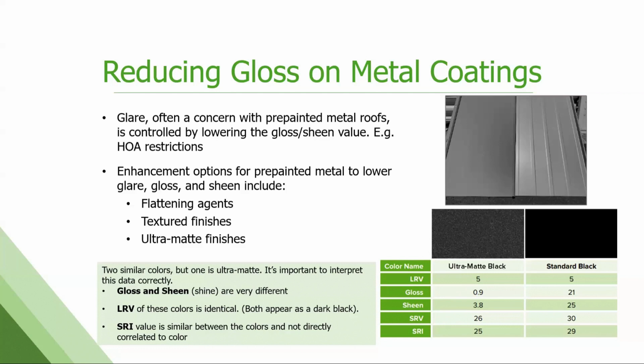We can kill the gloss or the sheen on a product a couple different ways. We can use flattening agents. We can do textured finishes, so now you're breaking up that light reflectance with a textured surface. And we do have ultra matte finishes available. The gray samples there, the top photo, those are numerically the exact same color. The panel on the left, though, is in a matte micro texture, whereas the panel on the right is a traditional mid-range gloss sheen product. That is what reducing gloss does to the physical appearance of the panel.